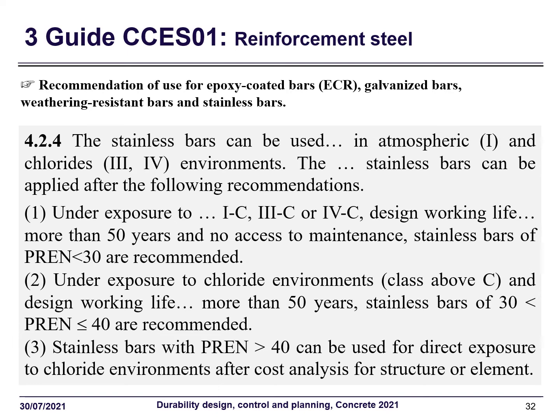And for reinforcement steel here, you can see that we recommend the use of epoxy-coated bar, galvanized bar, weathering-resistant bar, and stainless bar. Here, I just show you how we provide the requirement for stainless bar. You can see that we formulate the requirements in terms of the exposure, environmental action, intensity, and the service life, and also in terms of the PREN value of this stainless bar.